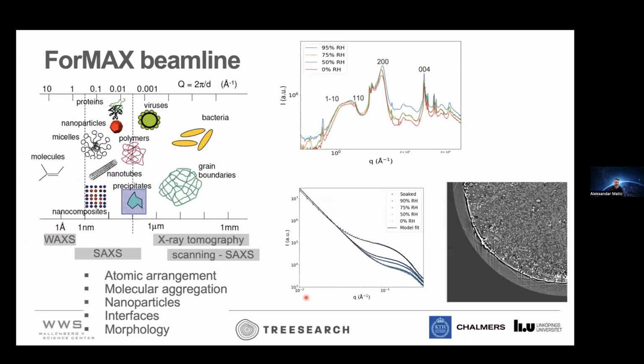Just to remind ourselves what the length scales we study are. When we talk about wide angle X-ray scattering, we are on the interatomic, intermolecular distances. Then we can go to small angle X-ray scattering, slightly longer distances, which gives us more the molecular aggregation, if we have nanoparticles, interfaces, and towards the morphology of the material. When it comes to X-ray tomography at ForMAX, we start from the micrometer length scale and basically go upwards, so you can really investigate what's there in your object.